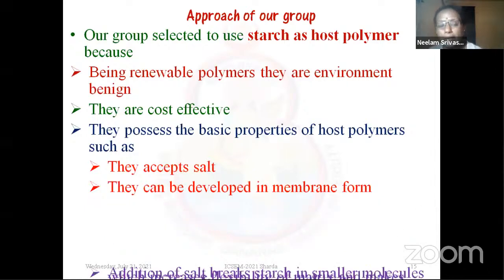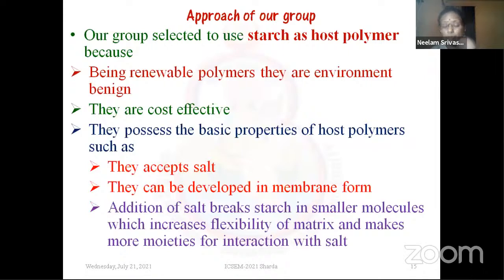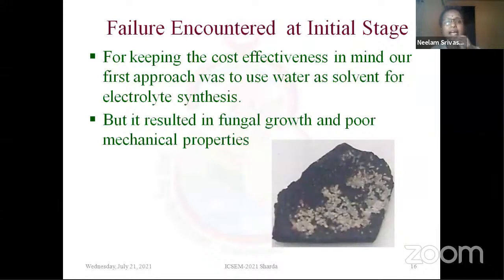And because of this, more amount of the salt can be added, and it can remain in the dissociated form, because moieties are available to interact with this salt. When we first tried this type of system, we encountered such a great failure, because the moment we left the system to dry, it ended up with fungal growth on the system, which not only decreased its mechanical property, but was affecting the electrochemical properties also.